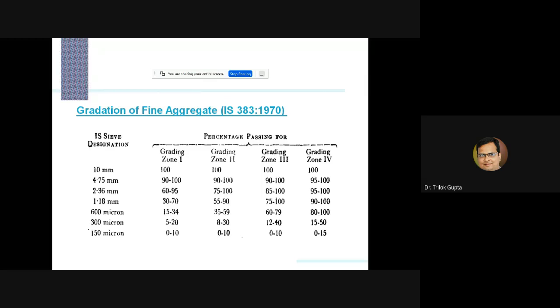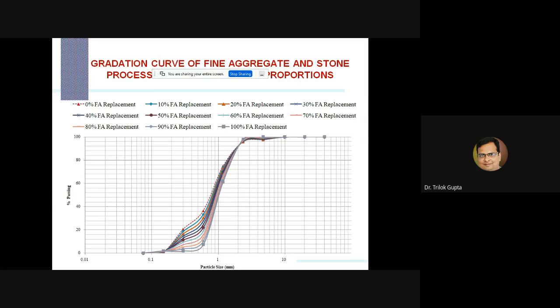So there are four classifications: zone 1, 2, 3, 4, and 4 is the finer one. So we will not discuss that now. This is the important curve basically. Now this curve represents the replacement level of the stone processing dust. We can observe from this curve that the fine aggregate has very few fine particles, meaning the percentage passing 90 microns is low. But when we go up to 100%, there are many more fine particles as compared to the natural river sand.